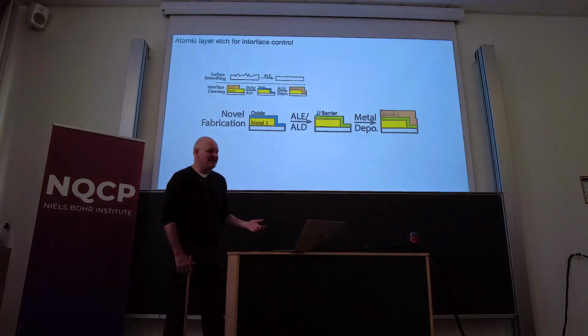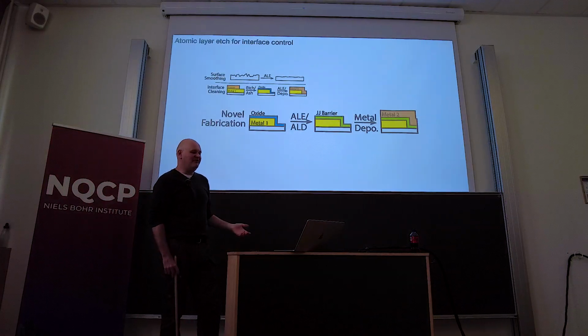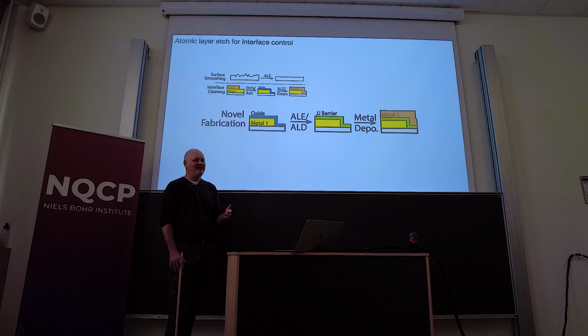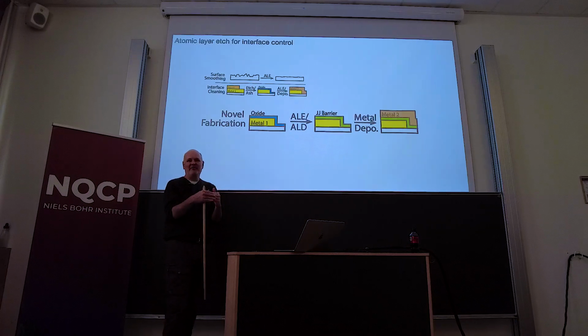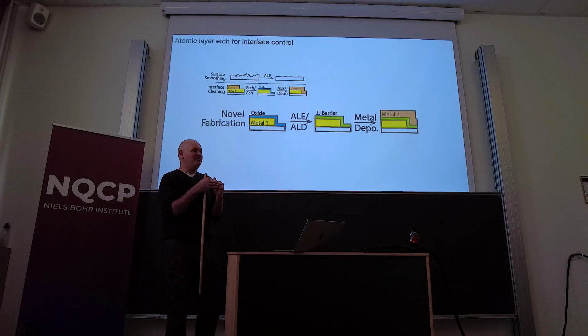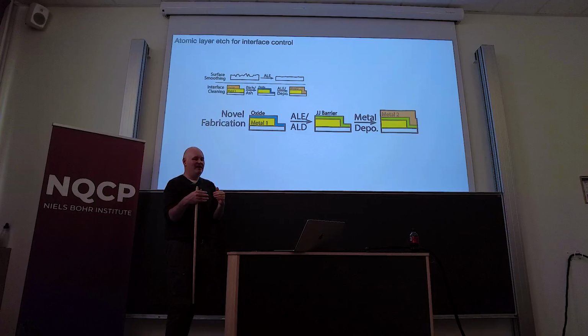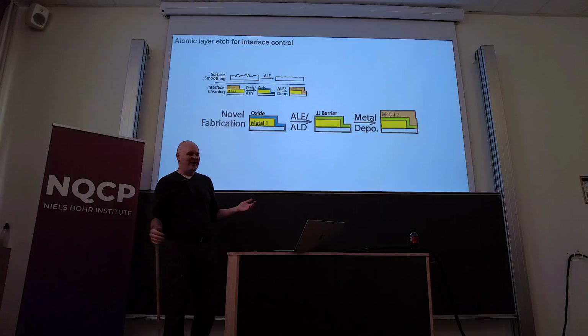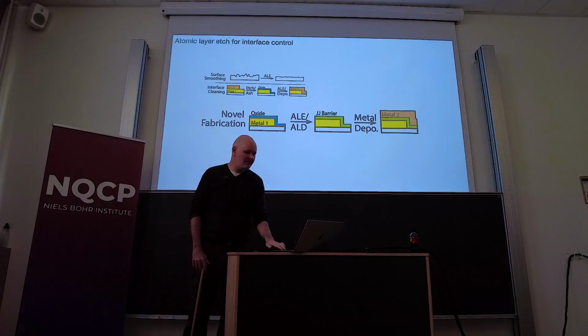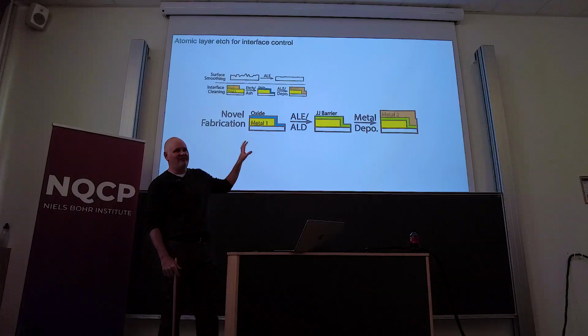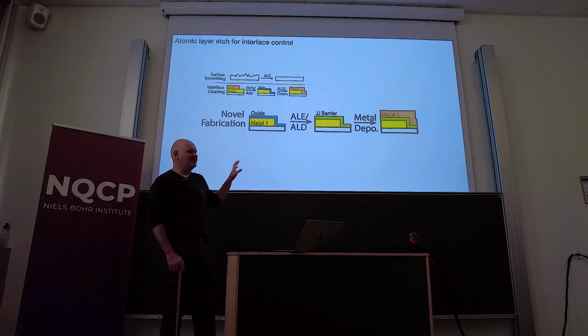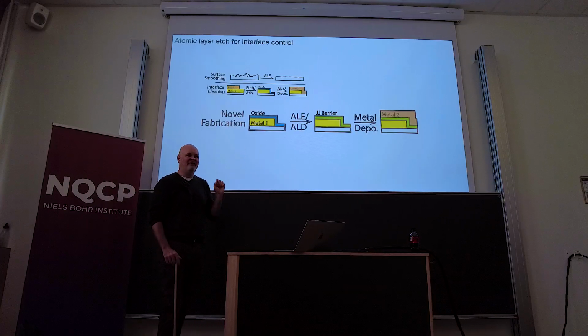And then the other thing it does is it allows you novel routes of fabrication. Because you're not tied to having your aluminum oxide happen in one chamber. If you can clean off that aluminum surface after it's been exposed to air, then you can add an aluminum oxide layer or whatever you want and fabricate a next layer on top of it. So it opens up a lot of different fabrication that's completely impossible now. But there's a lot of work to be done in just developing these etch processes. Atomic layer etch is something that's used very heavily in industry, but for very specific things that are not superconductors.